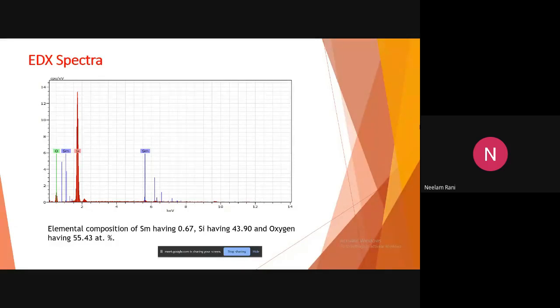Here, different peaks represent different elemental compositions of the present elements: samarium, oxygen, silicon. The large intensified peak of silicon shows that silicon is present in large amount, having 43.90 atomic percentage, and samarium has 0.67 due to low concentration of samarium in the silicon, and oxygen having 55.43 atomic percentage.